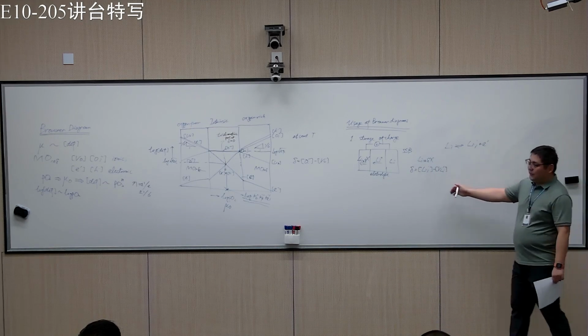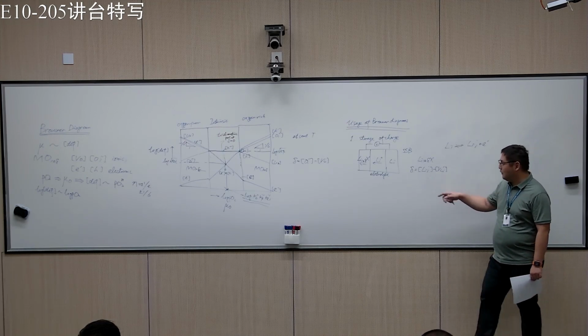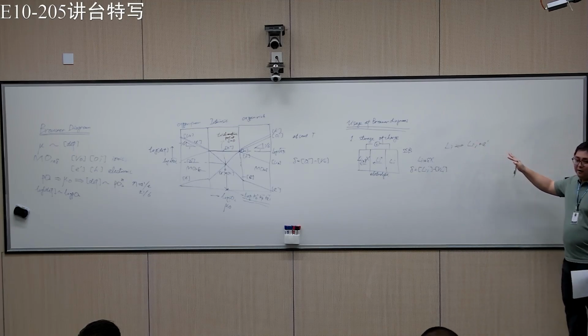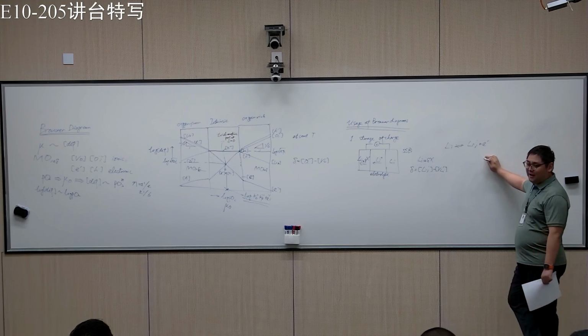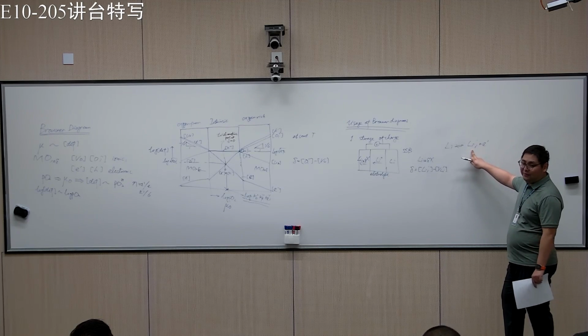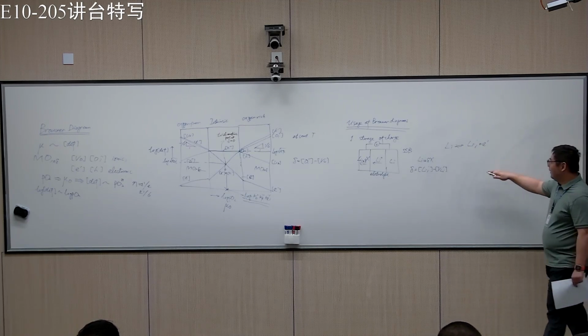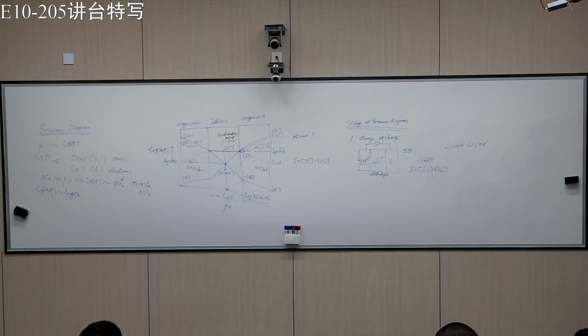This is how we store energy in the lithium-containing compound in the battery material. We store it in the form of both ionic defects and electronic defects. It's not very popular in the study of lithium batteries, because people usually just write normal lithium ions, but these are really non-stoichiometric, so you can understand them using the defect chemistry language.